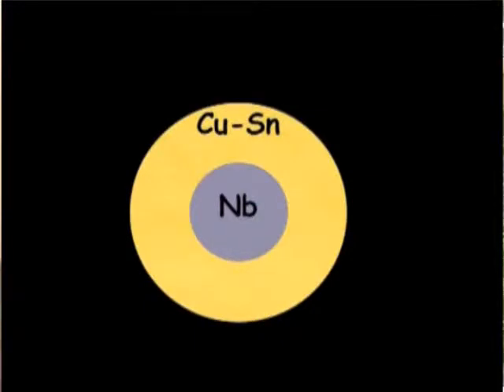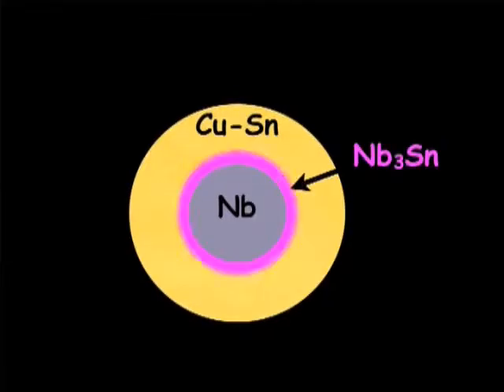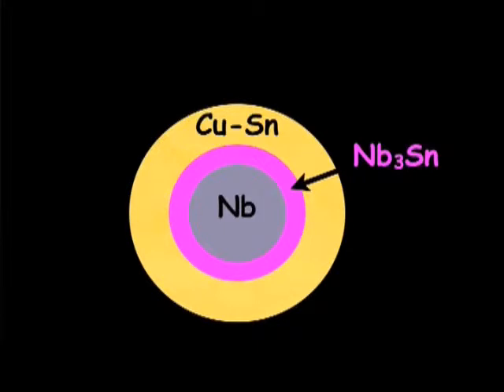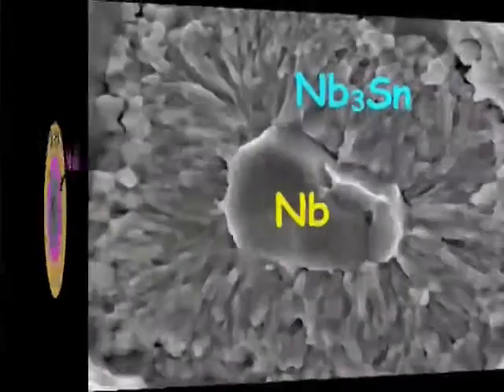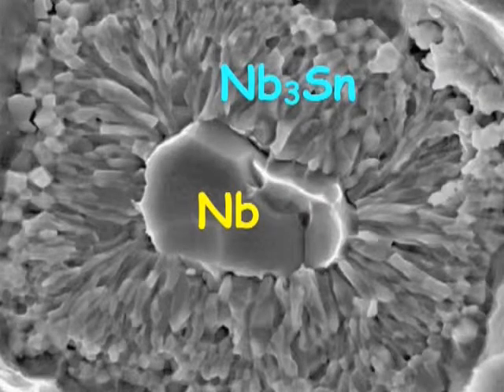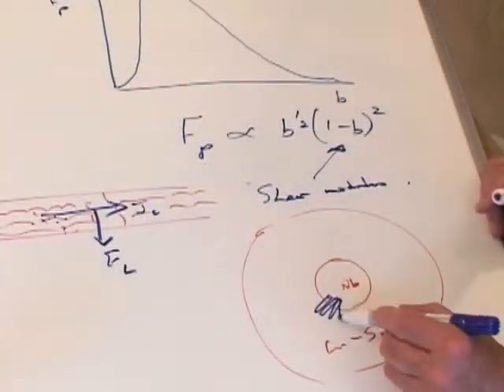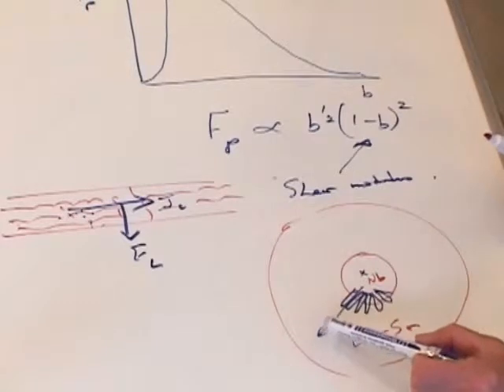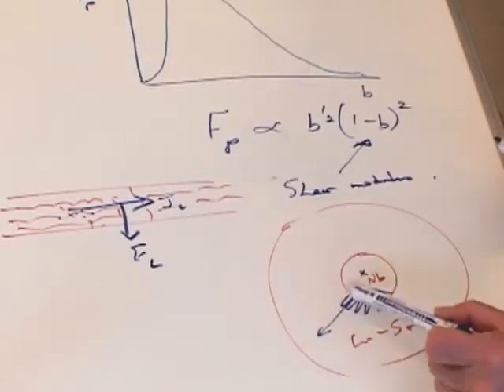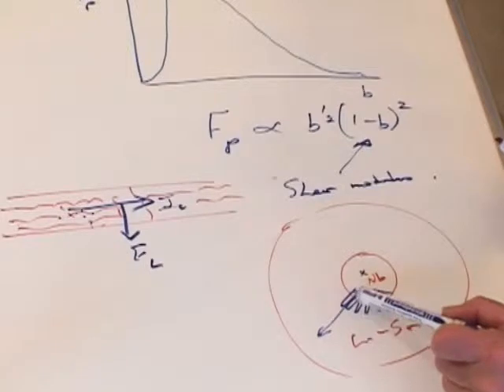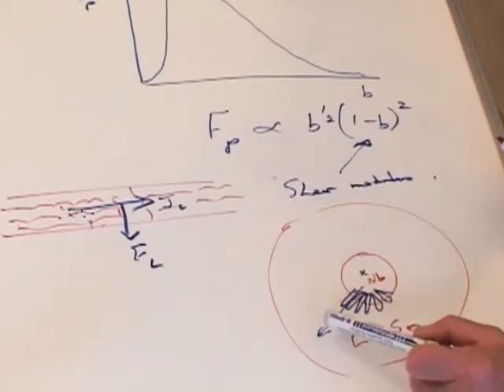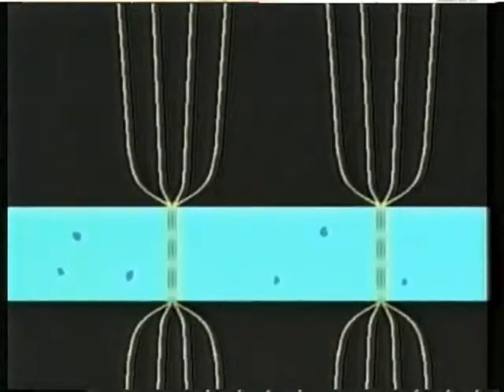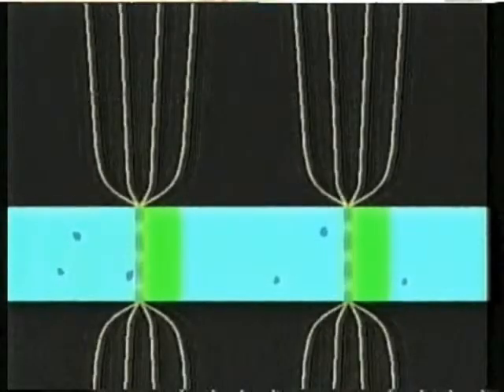We have core of pure niobium in a matrix of bronze. Under annealing, the tin reacts with the niobium to produce a layer of niobium-3-tin. And this grows in columnar fashion, and the grain boundaries do not offer hindrance to flux lines. They are able to slide down the grain boundary. So we can have part of the flux lattice pinned within the grains, and part shearing down the boundary. And what then governs critical Lorentz force is the shear strength of the flux line lattice.